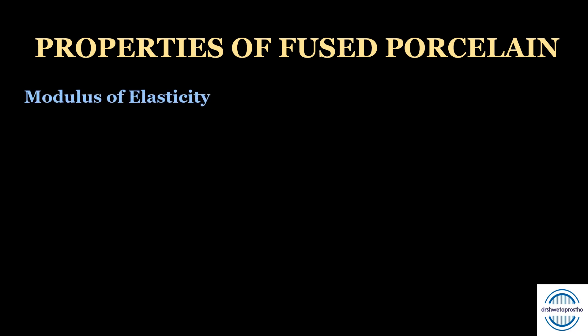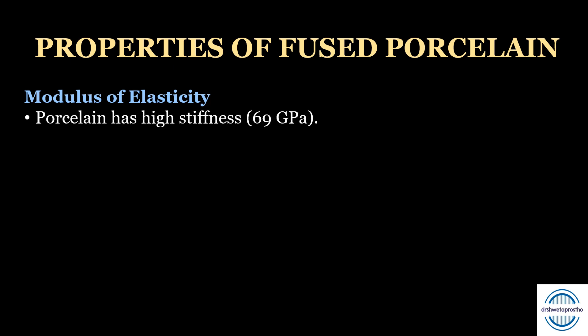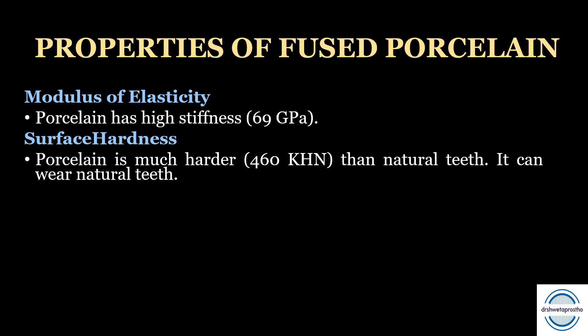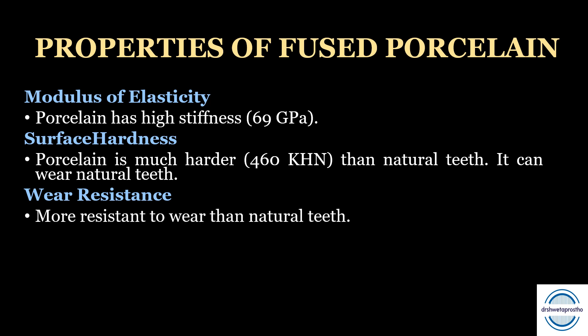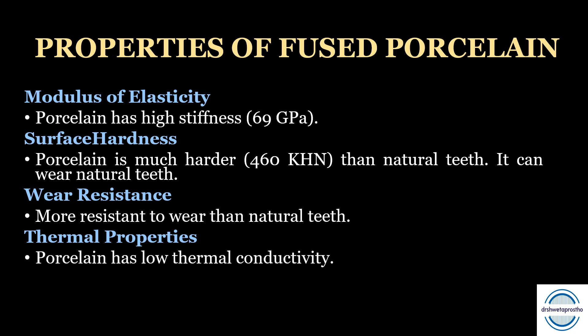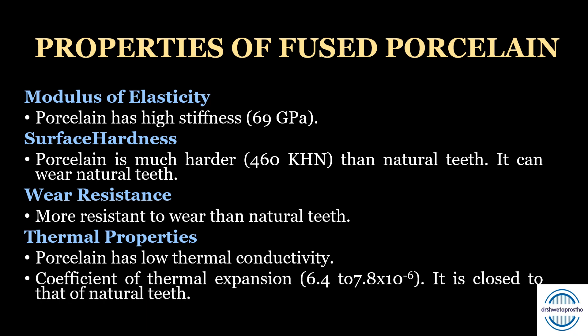Moving to other properties of fused porcelain: modulus of elasticity — porcelain has high stiffness with a modulus of elasticity around 69 GPa. Surface hardness — porcelain is much harder than natural teeth and can wear them. Wear resistance — porcelain is more resistant to wear than natural teeth because of its greater surface hardness. Thermal properties — porcelain has low thermal conductivity, making it safe on vital teeth. The coefficient of thermal expansion is around 6.4 to 7.8 × 10⁻⁶, close to that of natural teeth.